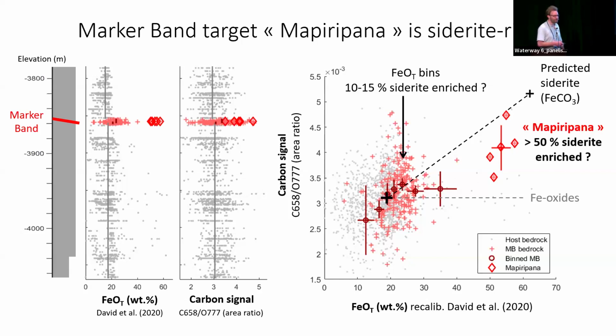Mapiripana. It's hard to pronounce, sorry, but we're going to have to pronounce it because it's key to this talk. And this one, as you see, is important for two reasons. It's the most iron-enriched target that we've seen with ChemCam. You see some points here in gray that are from sporadic detection of iron oxide at the millimeter scale. This target, all 5 points, are enriched in iron in a homogeneous manner, so it's a pretty homogeneous target at the millimeter scale. And secondly, it has a positive carbon detection, which directly places us above 50% carbonate in that rock. So the bulk of that rock is considerably enriched in iron and carbonate, and that's why we infer this is a siderite-rich target.